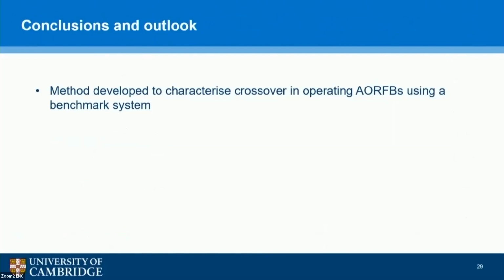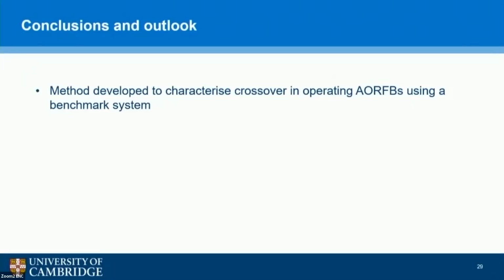So just to conclude, we developed a method to characterize crossover in an operating redox flow battery. And this has so far been done using a benchmark system. We've seen some evidence for quinone degradation in the catholyte side, which previously hasn't been reported. I think this also shows the strength of using in situ NMR, because if we were using ex situ experiments, it would be harder to understand where this signal loss had come from, depending on where you were sampling.